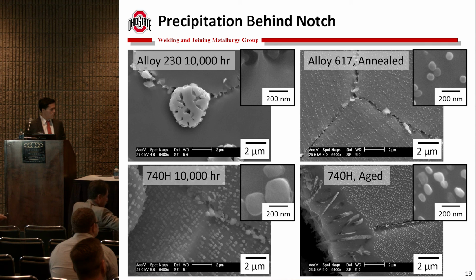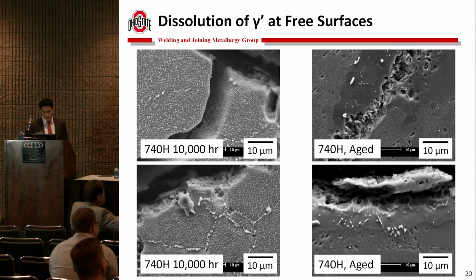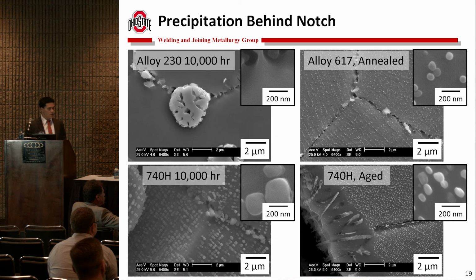precipitates adjacent to and all the way into this grain boundary. The interesting feature, though, is that the gamma prime dissolution seems to be more related to simply the presence of a free surface or exposure to environment, and for some reason only in the 740H which was aged only for 4 hours, and so within this 10,000 hours, the gamma prime must be stabilized beyond the point where it can dissolve in air. But I haven't really investigated this too much, and I need to. I suspect that this situation is a combination of discontinuous precipitation and the exposure to the environment.